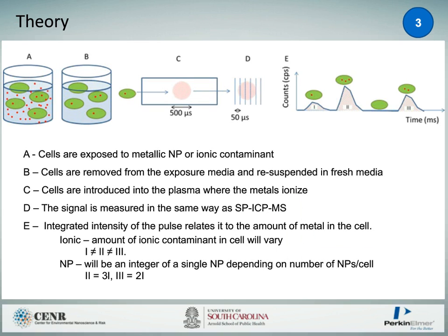So the theory behind this is in A, you expose your cells to a metallic contaminant, either nanoparticulate or ionic, and then you remove an aliquot of this, wash it out and resuspend it in a media of fresh water. From this point, in C, you introduce it to the plasma in the same way you do SingleParticle ICP MS, so you want one cell traveling through the plasma at a time. The cell will burst. The nanoparticles or ionic material inside it will also atomize and ionize. And then we go on to D, where you go back into the detector, and we're again using these very short dwell times so that in E we can get an integrated intensity per cell.